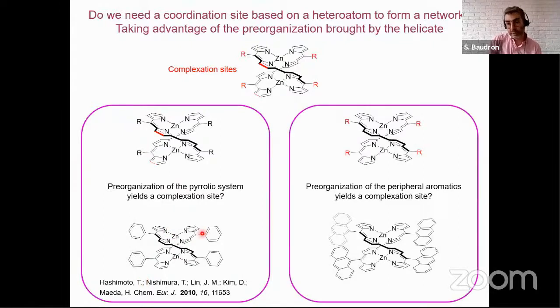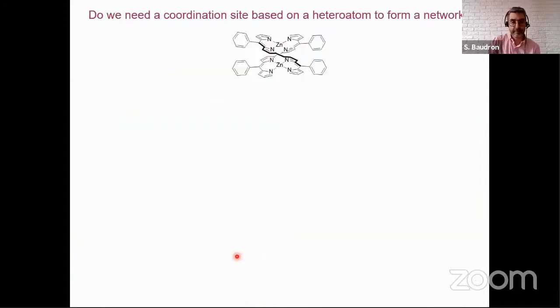Another thing we were trying to determine is whether we could use the pre-organization of a peripheral group. In this case, we introduced large aromatic units such as anthracene to see whether this could be used as a pocket for complexation of silver(I) cation. This helicate had been described by the group of Maeda in the literature, but its assembly with silver(I) cation had not been described.